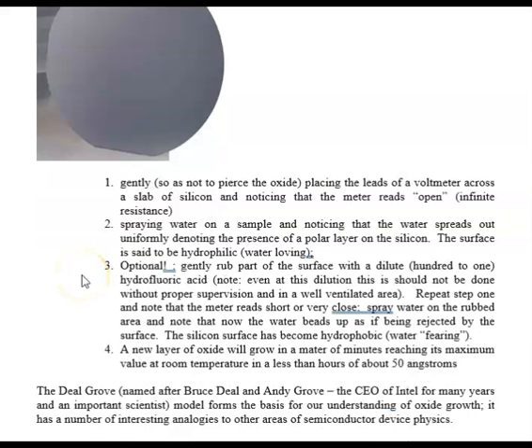There is another way to show this, which shows it in a much more convincing manner, but as they say, do not try this at home. I do it in class. I don't tell anybody. That's because it's not very safe. Anyway, you take hydrofluoric acid, HF. You can dilute it. We generally dilute it down for this experiment to 100 to 1. It generally comes about 10 to 1. I dilute it down to about 100 to 1, but it's strong enough. It's quite dangerous. So again, don't do this at home.